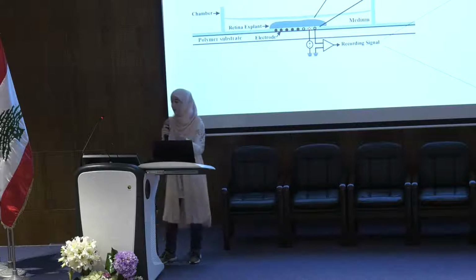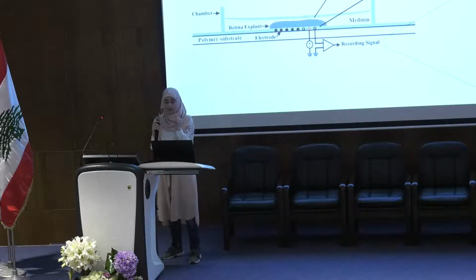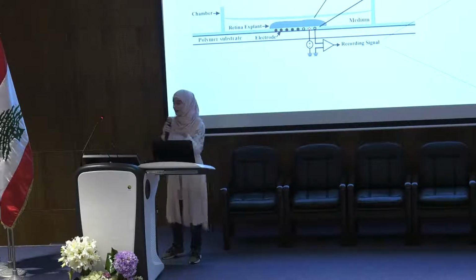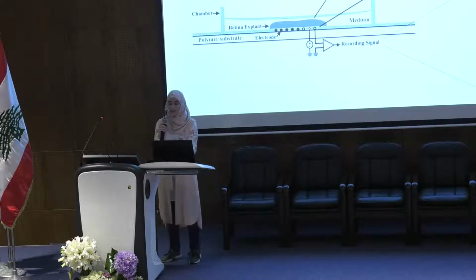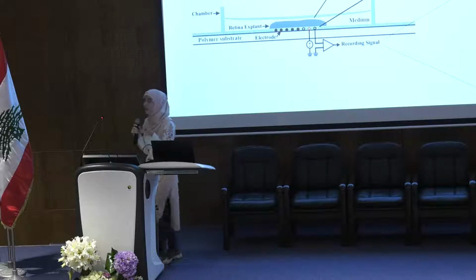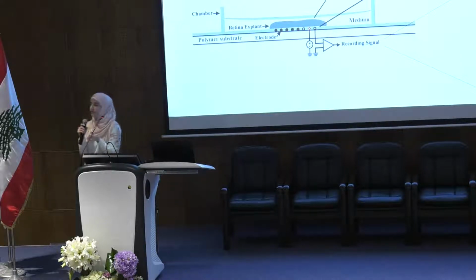Since the electrodes are able to record the activity of the neuron, we got the single unit activity. These electrodes are in the range of 50 microns. So they are pretty close to the size of the neurons, and they are able to record the signal from one cell.